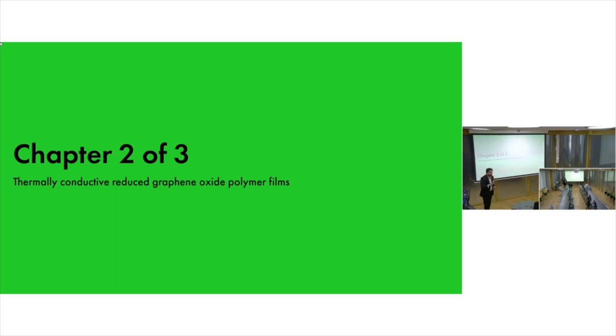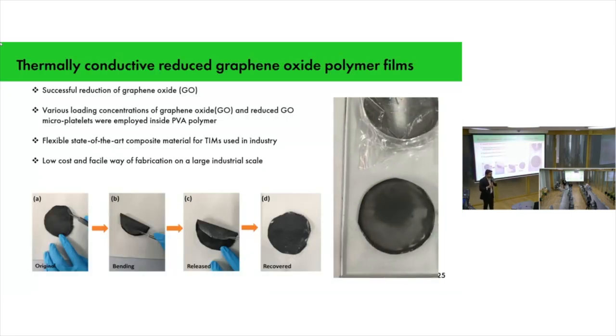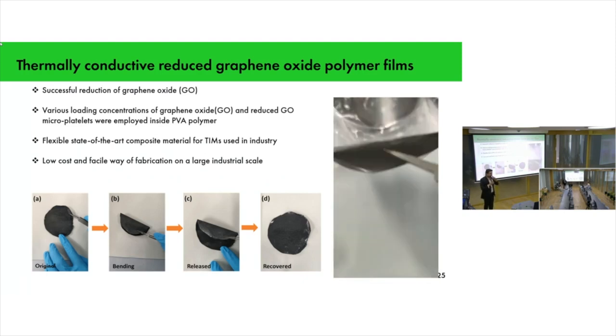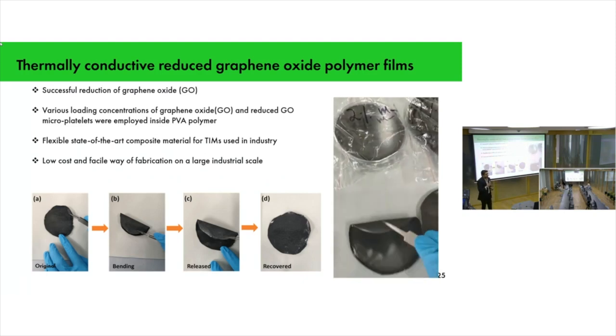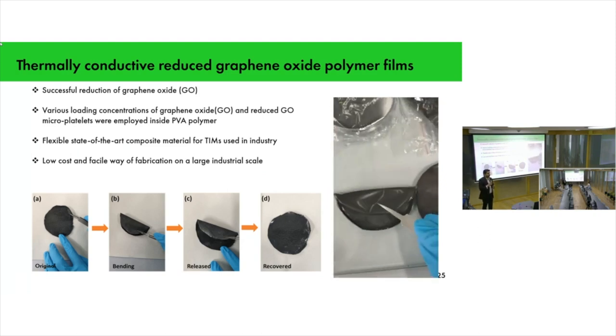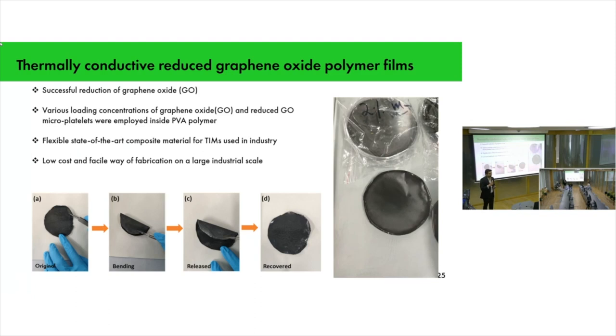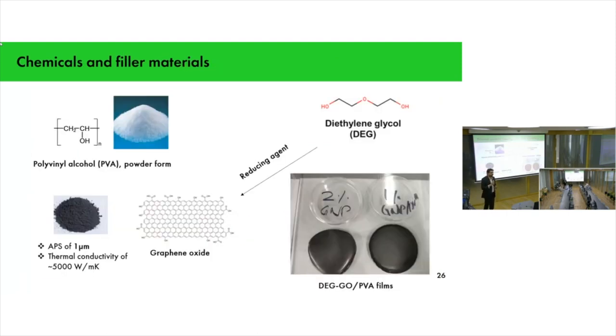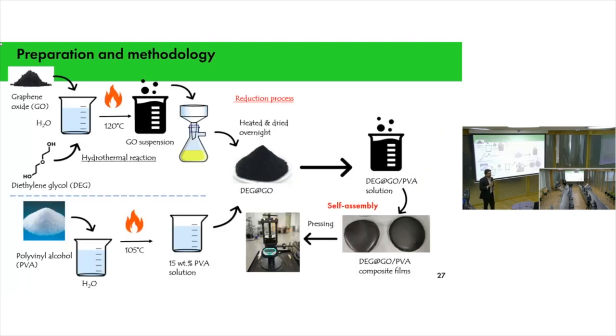So my chapter 2 is composed of thermally conductive reduced graphene oxide polymer films. I successfully reduced graphene oxide, and then I used different graphene oxide and reduced graphene oxide micro-platelets inside the PVA polymer to have improved flexible state-of-the-art composite material for industry. It is very low cost and its fabrication method is very easy for large industrial scale. I used diethylene glycol as a reducing agent for graphene oxide. And graphene, as you all know, has very high thermal conductivity of more than 5,000 watts per meter Kelvin, and with an average particle size of 1 micrometer, it increases the thermal conductivity to such a level.